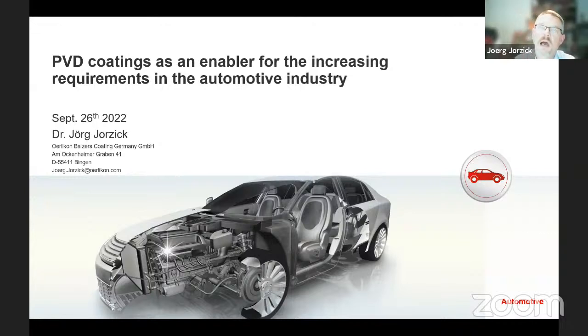However, there are applications where both components which are in tribological contacts are coated, and then typically we choose the coatings for both sides slightly different, so that there's at least a difference in hardness, so that one part can always be used to do this running in, and then the other just helps to stabilize the system. But especially for the carbon-based coatings, this running in is essential for the tribological performance.